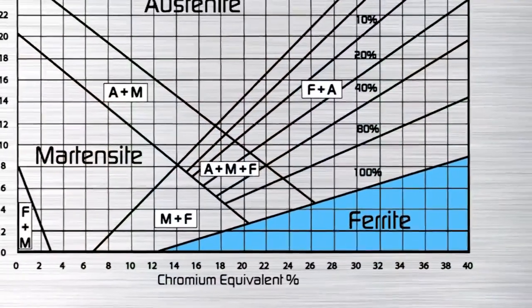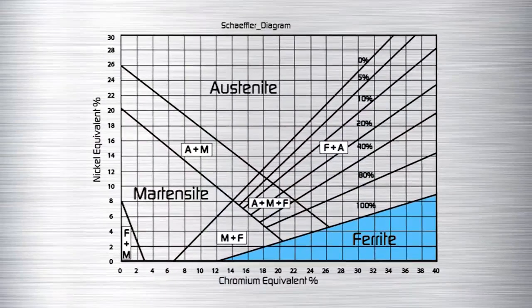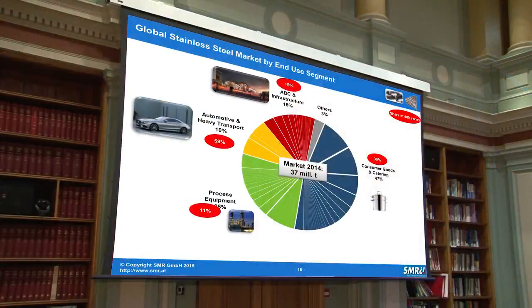Ferritic stainless steels, which contain either no nickel or much lower levels than austenitic stainless steels, are growing in popularity as a result of increasing nickel costs and have already gained a 30% share of the stainless market. The most common variants contain either 12% or 17% chromium, and specific sectors such as automotive are growing at 7% per annum.